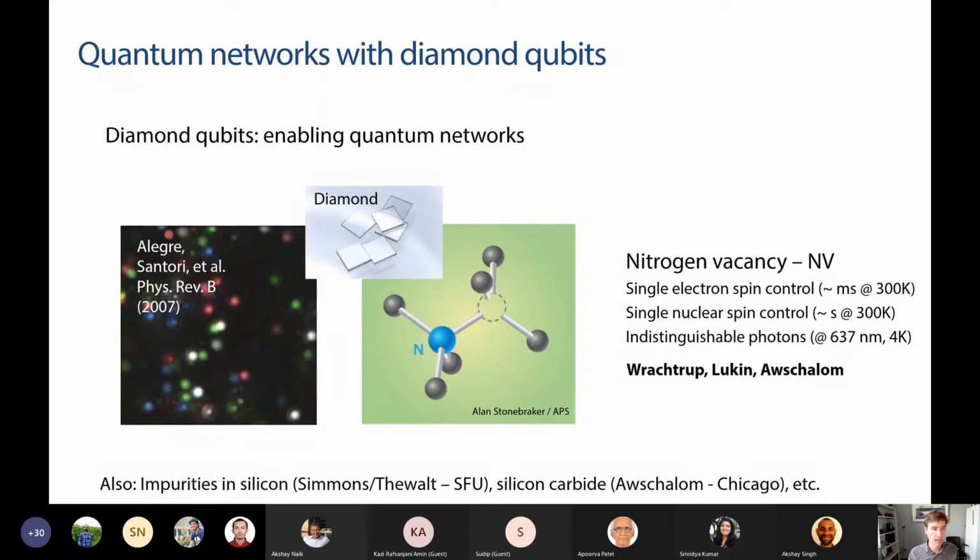and they can do this strongly enough that you can actually optically measure single impurities. This is a confocal microscope image of a diamond sample. The field of view is probably about 100 microns by 100 microns. Each of these bright spots is light coming from a single impurity in this diamond sample, and the color in this case corresponds to polarization and not wavelength. In principle, the photons coming from these emitters are all identical, although this in practice is a little bit difficult to achieve.